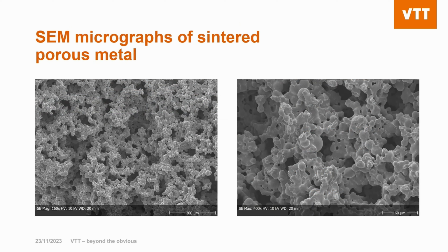And these are scanning electron microscope images of those porous materials we have manufactured for our reactor, and you can see that the actual surface area is in practice quite huge because of this porosity. And it's still open enough so that the gas flows through these walls from inside to outside.